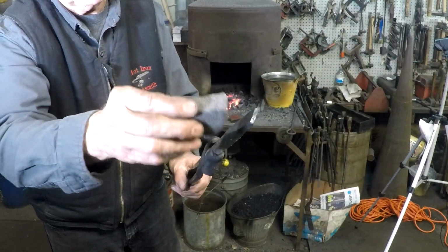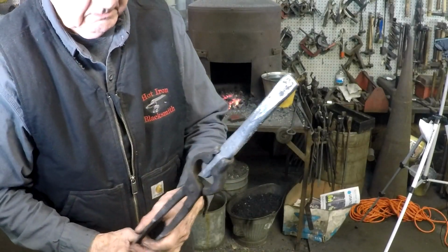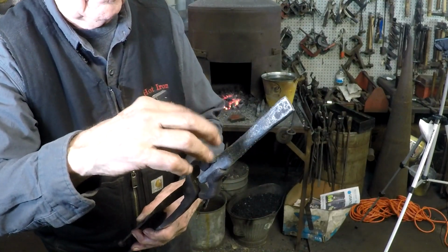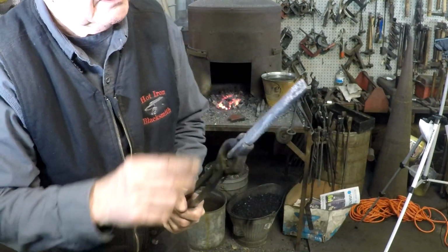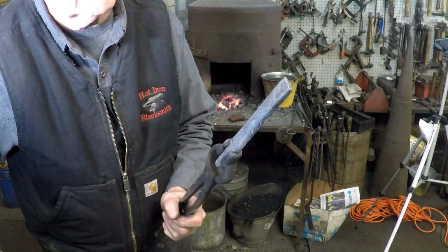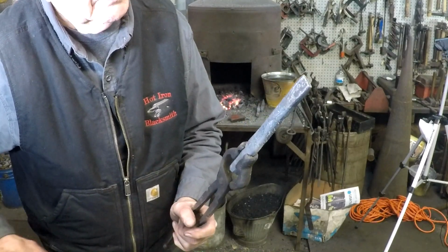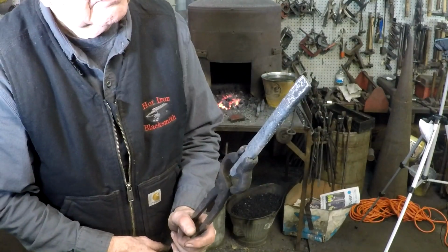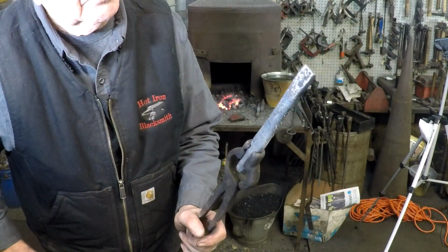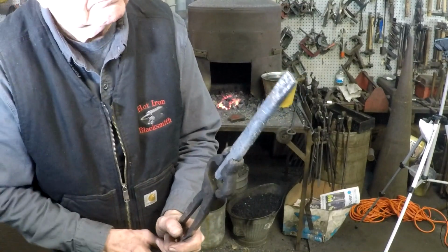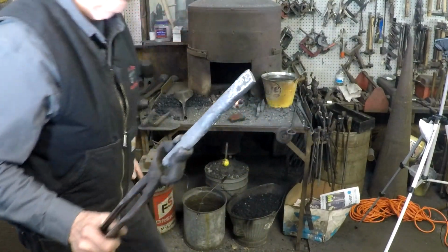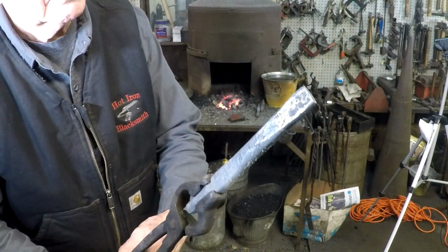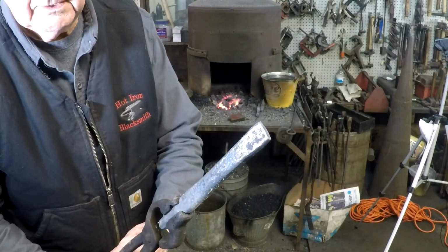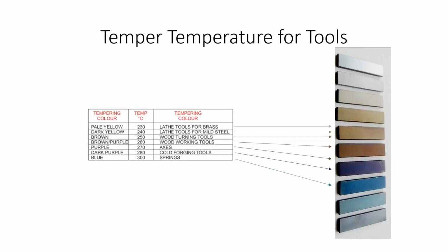I'm going to re-scrub it with this grinding stone. I would really like there to be enough heat in the residual part metal of the punch to be able to reheat the end all the way back to the brown color on the very tip. We can see where I ground it with the stone. It was picking up some turquoise and some peacock colors. So as those colors progress, we can see the browns starting to form out in front of those brighter colors.